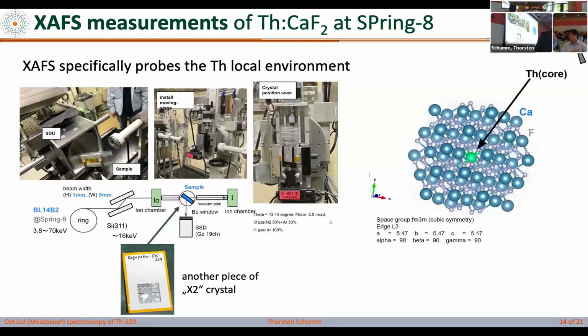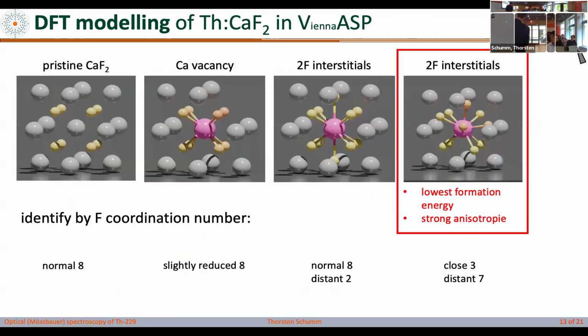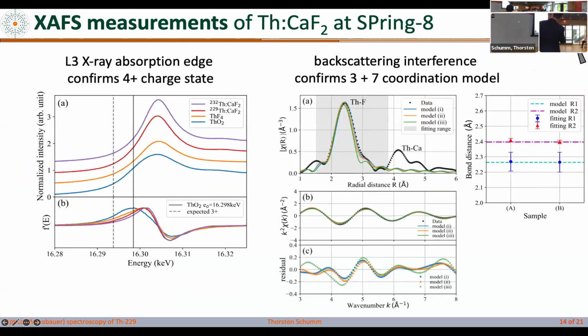And there's something amazing happening. I'll go back here. So when this electron goes out from here, it essentially emits as a spherical wave. But then it sees the scatterers around it, and there's a back reflection, and this one is still coherent to some extent. So there's an interference effect on top of this absorption signal. If I increase the ionization energy, there are backscattering resonances, and I see an interference pattern. This interference pattern, if I Fourier transform it, tells me where the nearest neighbors are and how strong they are, how many they are.